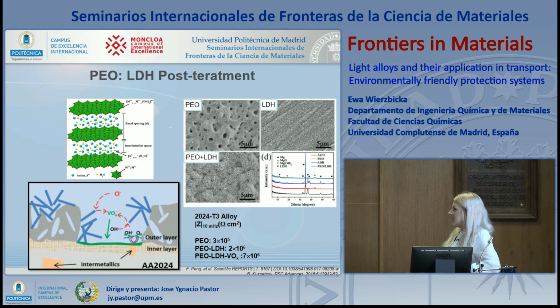One of the latest developments is combining PEO treatments with a very successful conversion coating, which is LDH. This is the picture of the PEO itself, and this is the combination of PEO with LDH. By application also of corrosion inhibitors, we can significantly improve the corrosion protection.